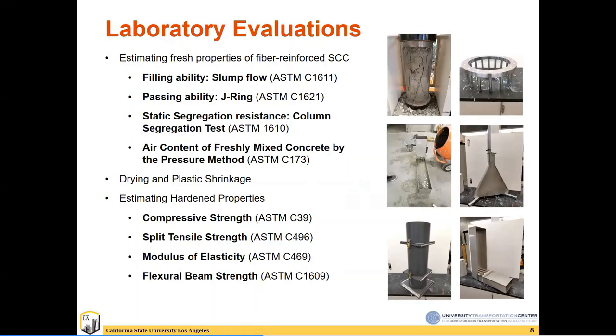In terms of laboratory evaluations, the fresh properties of the SCC, except for the regular slump test, there are some other specific tests that were designed and developed by ASTM and AASHTO to evaluate the properties of the SCC. The filling ability is evaluated through the regular slump tests, and sometimes they do an inverted cone slump test for SCC. Passing ability could be done through a J-ring test, as you can see on the top right here, that it basically simulates the reinforcement inside the formwork and sees how the SCC mix can flow through the reinforcement.